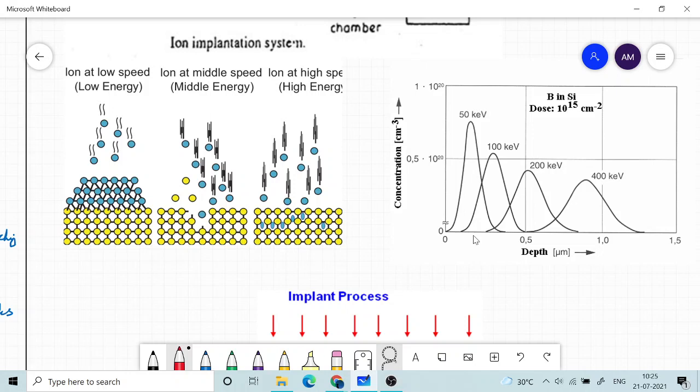Now as you can expect, these are high energy atoms, and they are going to disrupt the crystalline nature wherever they fall. Okay, so it will fall into the crystal wherever the photoresist is removed after the lithography. If the photoresist is there, photoresist is usually a thick layer, 500 nanometer thick, and therefore it will stop these ions, it will not let them enter into the silicon substrate, so it will not get doped. But wherever the photoresist is not there, ion implantation will go underneath and get stopped at different distances depending upon